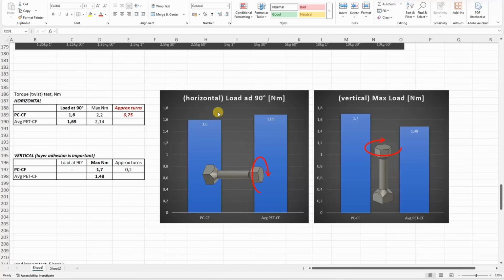Printed in horizontal position, load in 90-degree rotation, and this is the vertically printed maximal load. And it is typical that we can see similar numbers, of course different break type. Compared to the average PET-CF, this is a very similar value. Here, very small advantage on the PCCF side compared to the average PET-CF.